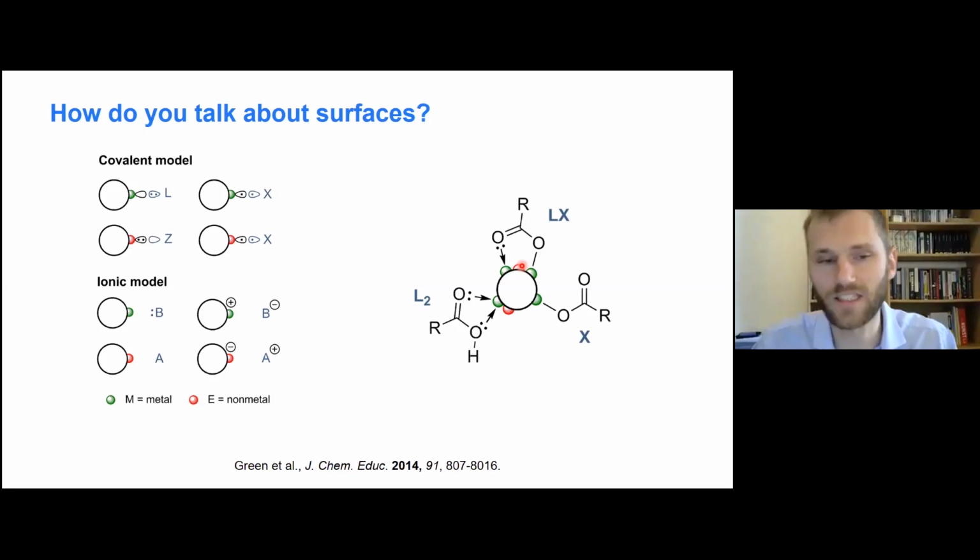And what you're asking is basically a desorption of the Z-type ligand. So this is the equilibrium nanocrystal-Z, with an equilibrium arrow to nanocrystal plus Z. That reaction is obviously also dependent on the solubility of the Z-type ligand. In the case of cadmium oleate and cadmium selenide, the binding affinity is so strong that the solubility does not play a role. But in the case of lead oleate, this binding affinity is rather weak, which means you can influence it with the solubility. I see. And then what we also have is data of more polar ligands.